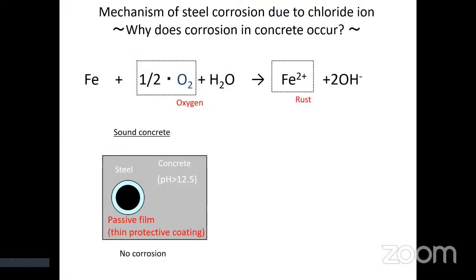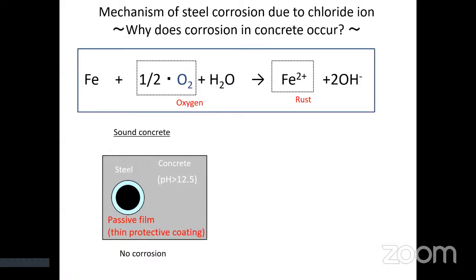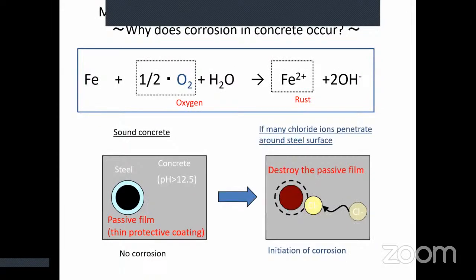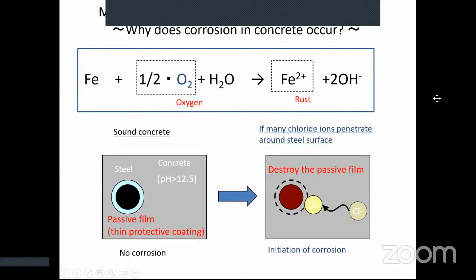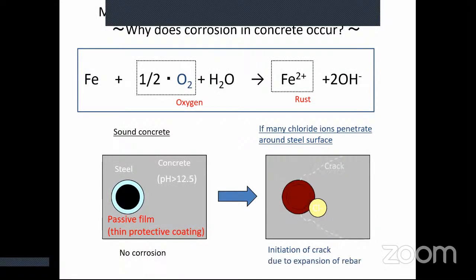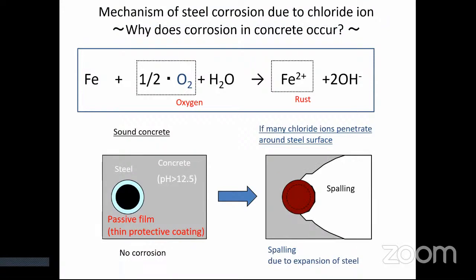From now, I'll explain the mechanism of steel corrosion. This is chemical reaction formula of corrosion. Iron reacts with oxygen and water. Then, rust is formed. Here, in the sound concrete with high pH, no corrosion occurred due to existence of passive film formed on the steel surface. However, if many chloride ions penetrate around the steel surface, passive film is destroyed and corrosion initiates. And then, cracks and spallings occur due to expansion of rust.